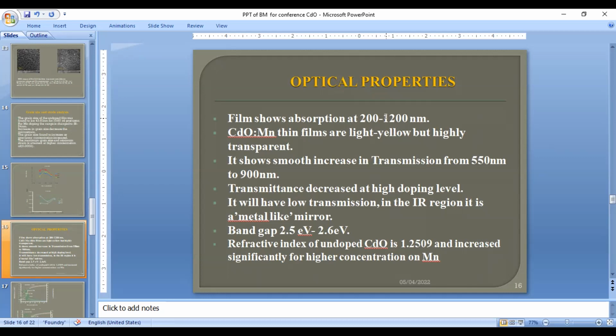The band gap we get is 2.5 eV to 2.6 eV. The refractive index of undoped cadmium oxide is 1.2509. It increases significantly at higher concentrations of Mn, at the various doping levels.